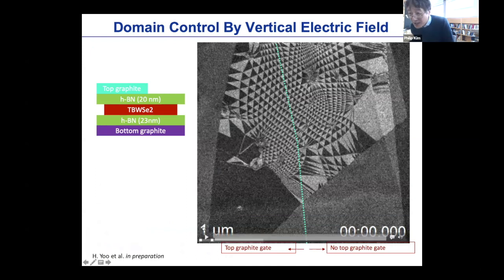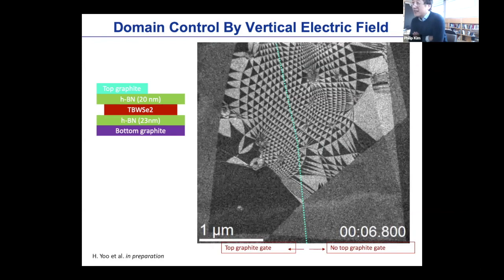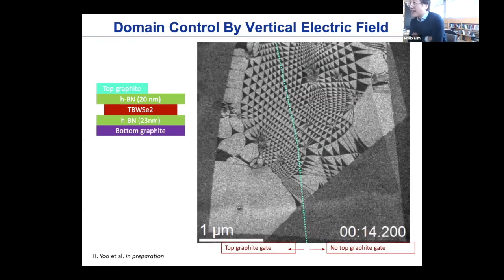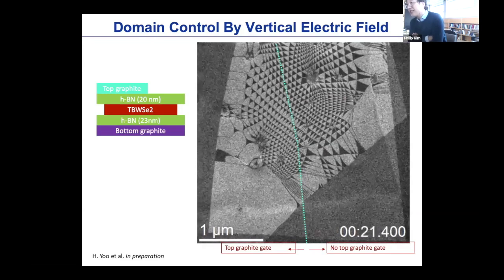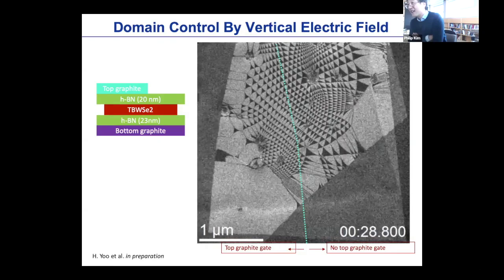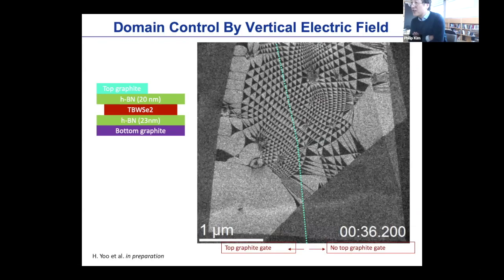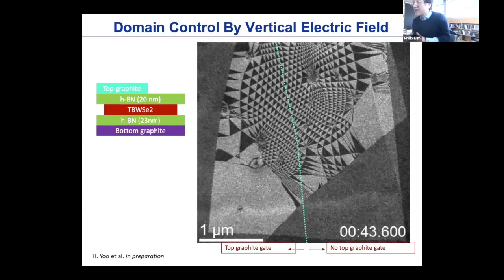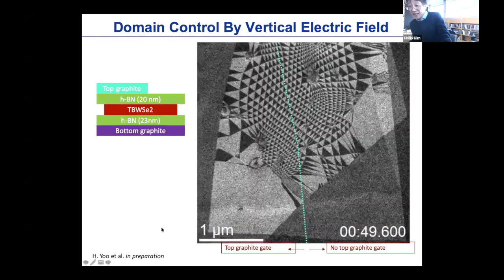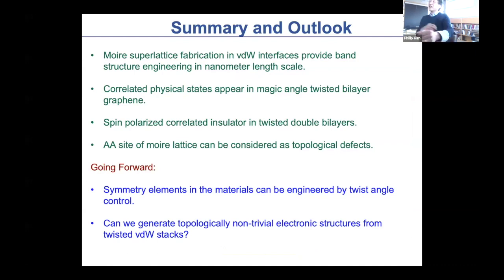So I will close it down by showing this movie. It shows that one can create these Moire patterns and put top and bottom gates so that one can control the displacement field. Now, this is TMDC layers, and in TMDC layers, all the Moire domains contain built-in dipole moments, such that when you apply the displacement field, this dipole moment couples with the electric field, such that the domain size becomes smaller and larger, right? So especially when dealing with these twisted bilayer cases, by applying this displacement field, not only do we change electronic properties, but in a sense we also change the lattice properties, lattice size, just by this electric field. So that's one thing I want to mention as another interesting opportunity.